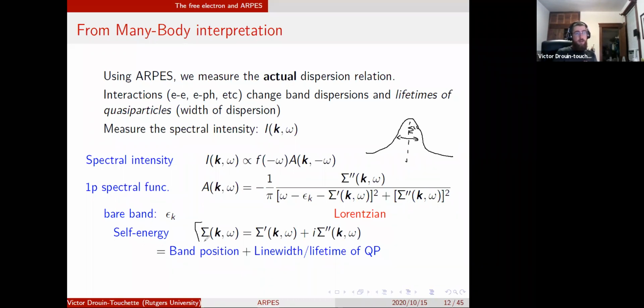The self energy is something that condensed matter theorists really want to calculate, because it encompasses all of the many-body effects on the electronic quasiparticle. It shows you how much the band of the electrons has been renormalized, shifted, and it also shows you that this quasiparticle only has a certain lifetime. After some time, this quasiparticle will break down, and that effect results in broadening, expanding all of your energy levels so that they look like Lorentzians.